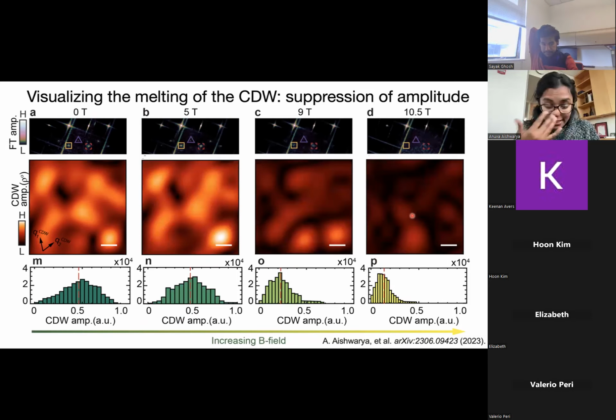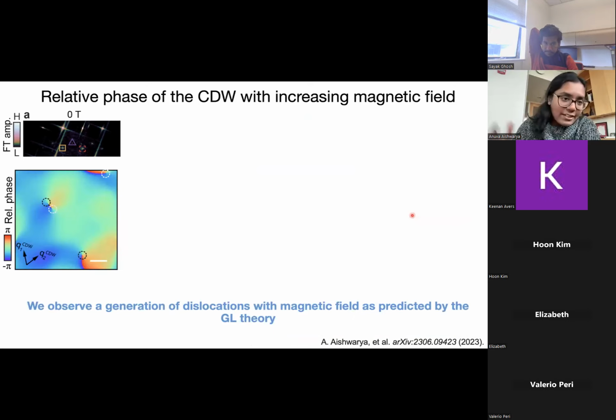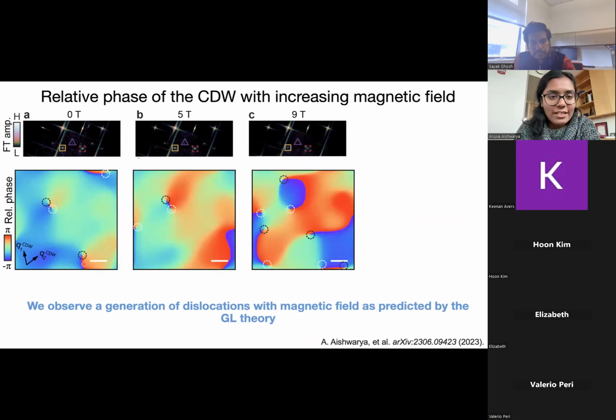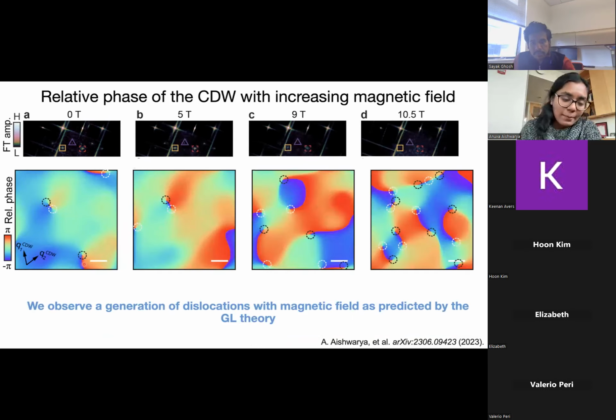And this can get clearer if we look at the relative phase. If we look at the relative phase, we have, let's say, two dislocations to begin with. And as we increase magnetic field, we see an increase in the number of dislocations. And this is exactly what was predicted by the Ginzburg-Landau theory.